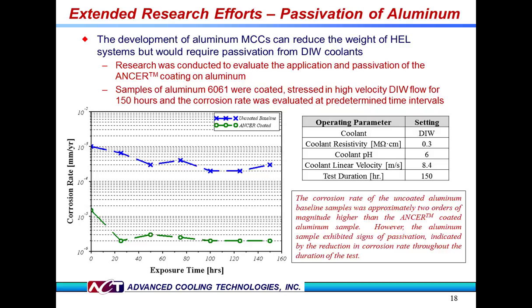We have been asked many times if the benefits we have shown ANCER coating to provide on copper can be realized on other materials, especially aluminum, which is lighter and cheaper than copper, but still suffers from the same corrosion-erosion issues. For military applications, this would be particularly beneficial for high-energy laser devices, which are striving to become more transportable and are subject to weight limitations. Testing has been initiated to see if ANCER can become a reliable passivation coating for aluminum, and here we show initial results under the test conditions detailed on the right.